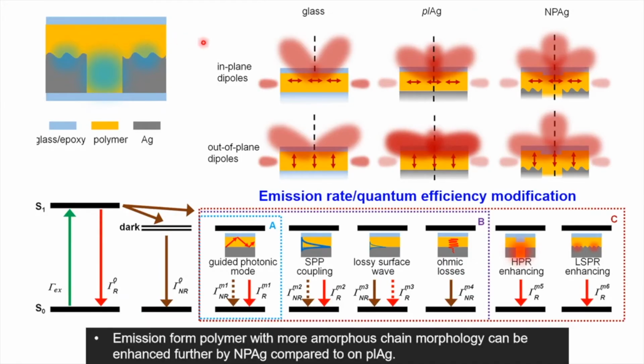This is a summary of the findings of this study. As we went over, there are three contributions to the photoluminescence enhancement. There's the excitation modification that's caused by localized surface plasmon resonances of the pores at the excitation wavelength, so they're essentially enhancing absorption of the incident light into the semiconductor. The emission direction modification also occurs. You can see, for example, compared to glass, the planar silver will typically create less emission coupling to the substrates. However, with the nanopore silver, you'll tend to get more emission in the substrates, as well as quite a lot of emission directed normal to the plane of the substrate, due to light scattering.